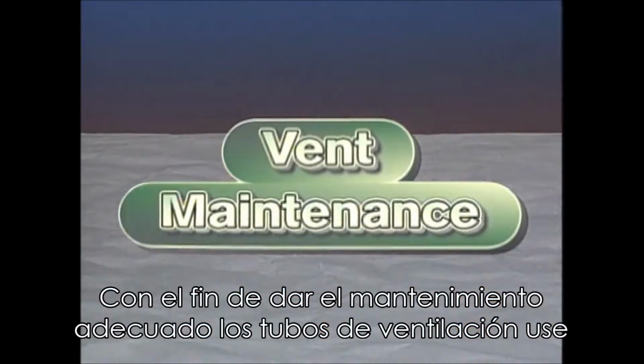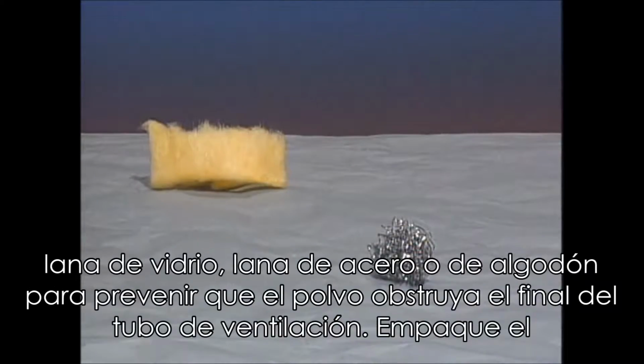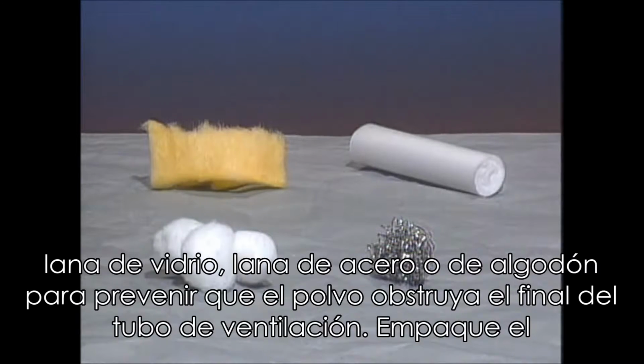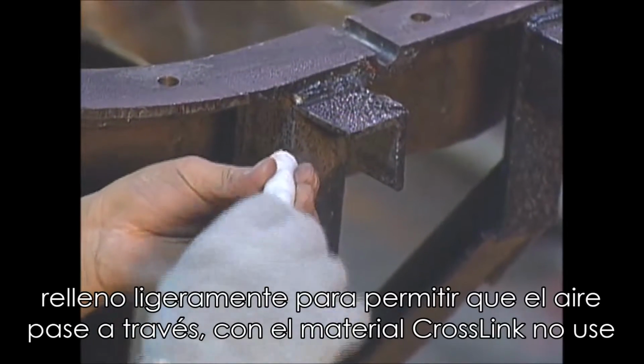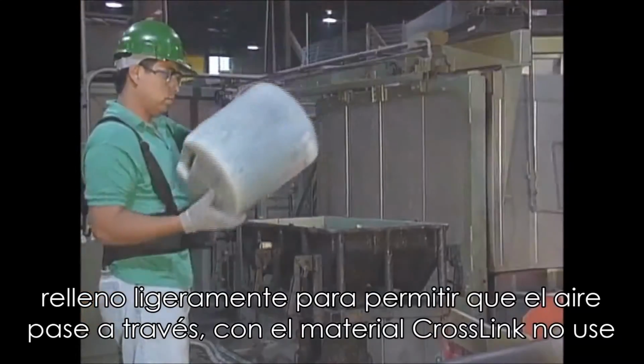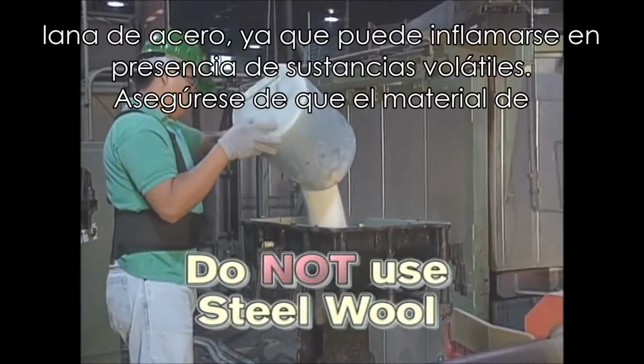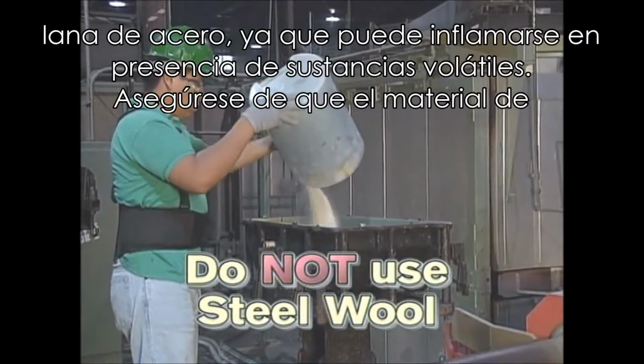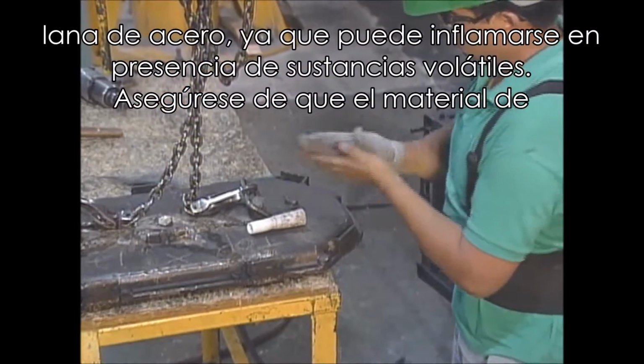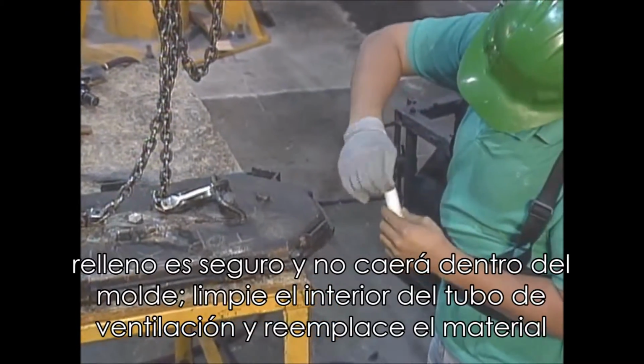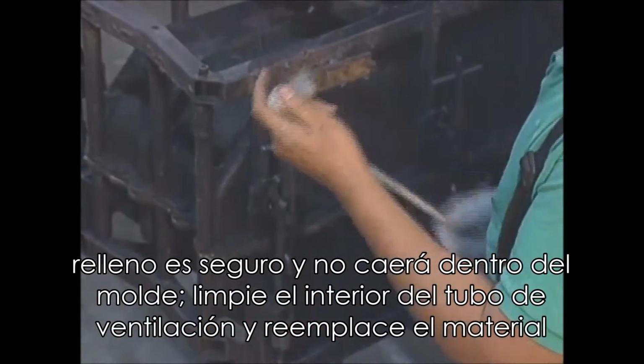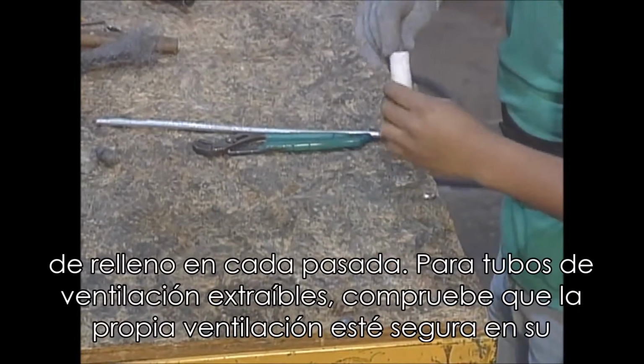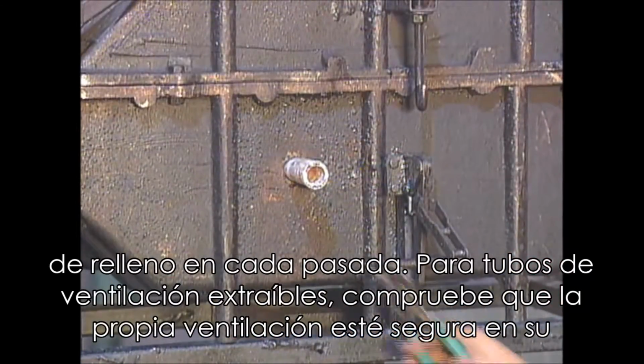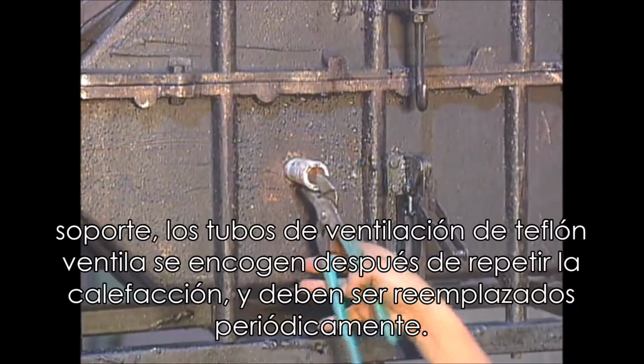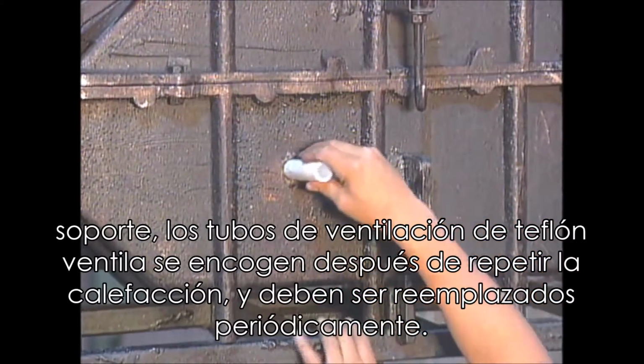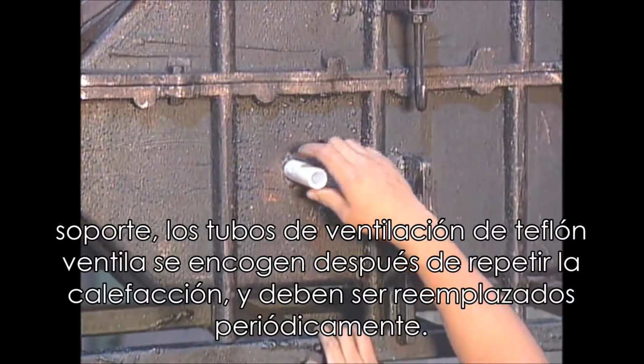In order to properly maintain vents, use glass wool, steel wool, or cotton to prevent powder from clogging the end of the vent. Pack the filler lightly to allow air to pass through. When molding cross-link material, do not use steel wool, as it can ignite in the presence of volatiles. Make sure that the filler material is secure and will not fall into the mold. Clean the end of the vent and replace the filler material on every pass. For removable vents, check that the vent itself is secure in its holder. Teflon vents shrink after repeated heating and must be replaced periodically.